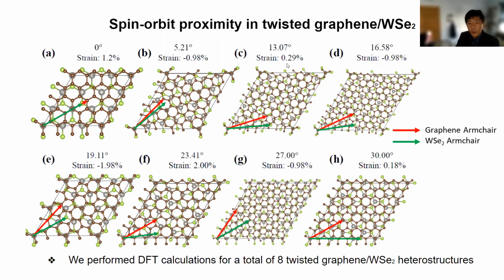Because of that, it's not easy to find a supercell where they are exactly commensurate. So to make it commensurate, you have to strain one of the materials in order to force it to make a supercell. And these are the few angles that we are able to find where the two materials are commensurate, where the strain is less than 2%. One can also construct a supercell of other angles, but then the strain will be quite large. So these are the 8 configurations that we are able to identify where the strain is less than 2%.